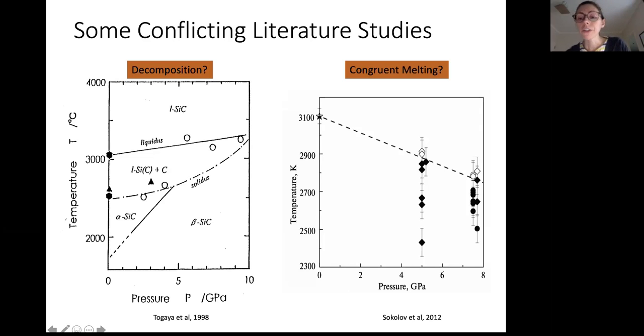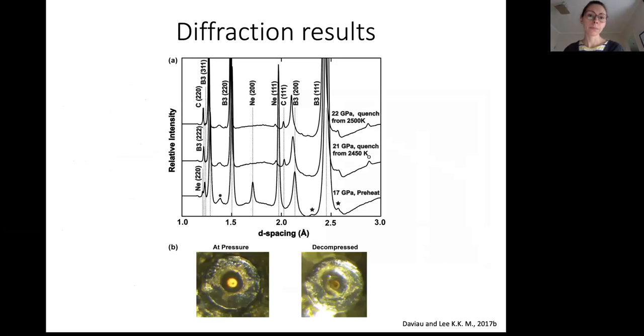This is in direct contrast, though, to a study that came about 15 years later, where they saw that at high pressure, silicon carbide began to melt congruently, so without breaking up, and that as you increased pressure, you needed less temperature. So what we wanted to do was try to make sense of these results and extend these experiments to higher pressures.